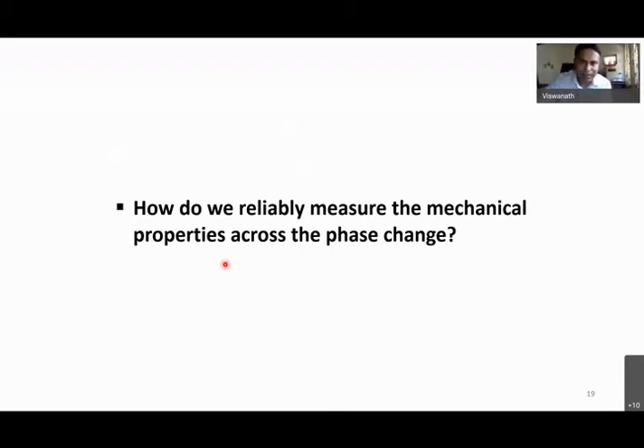In fact, the reason I'm asking is, can we reliably measure the properties across the phase change? Most of the time we do, for example, micro indentation or nano indentation as a function of temperature. But as correctly asked by Guru, we do not know where the phase transformation is nucleating and how the phase boundary is moving. So I'm doing an indentation, maybe taking the transition temperature from other measurements like DSC and so on. But locally, when we do the measurement, no one can be sure whether the place where I'm trying to do the indentation is already in the monoclinic state, the tetragonal state, or at the phase boundary. So there can always be a difficulty in measuring properties reliably during the phase transformation.